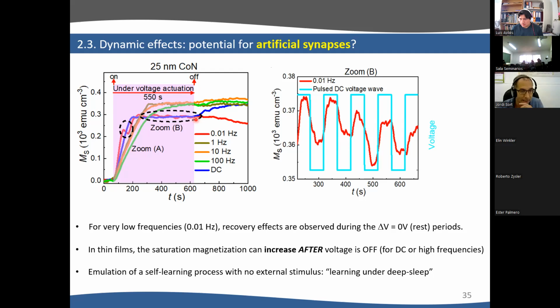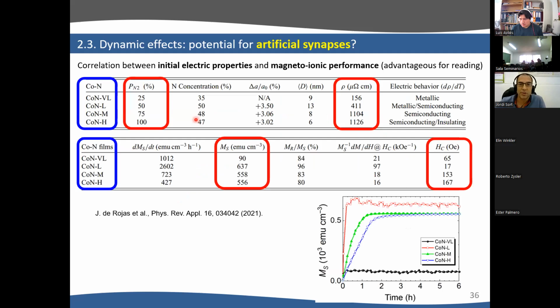But before explaining why this happens, it is important to show that there is a correlation in this cobalt nitride between electric properties and magnetic properties. Why? Because the change in magnetization is not how the brain works. The synapses are interconnected by electric stimulus. So it is very important to have a correlation between electric resistivity and change in magnetization. And actually there is such correlation, and we have this paper published this last year.